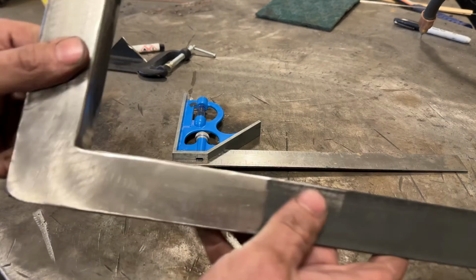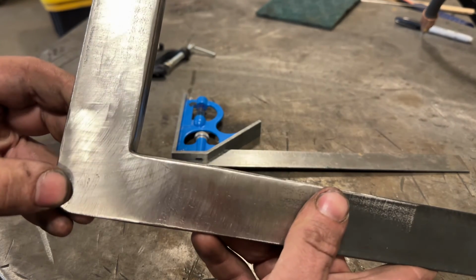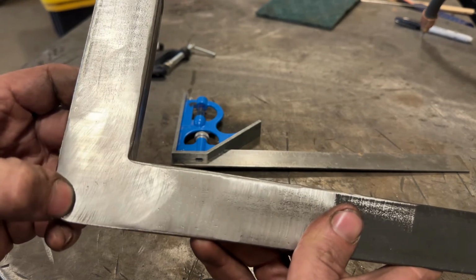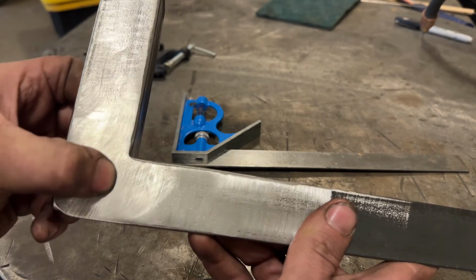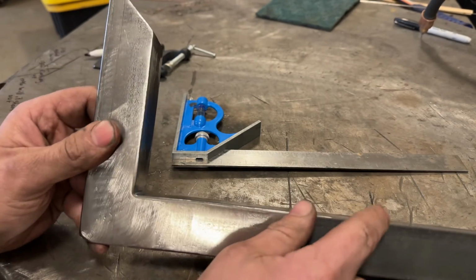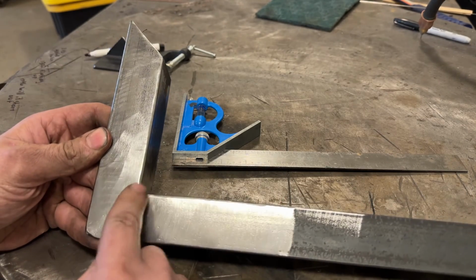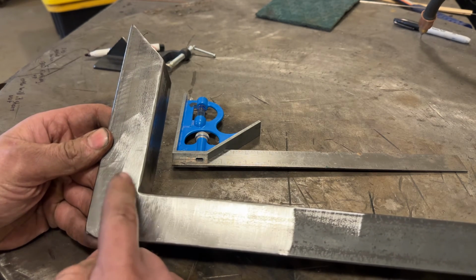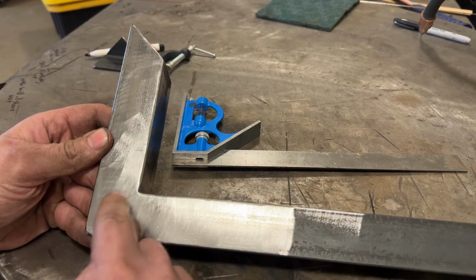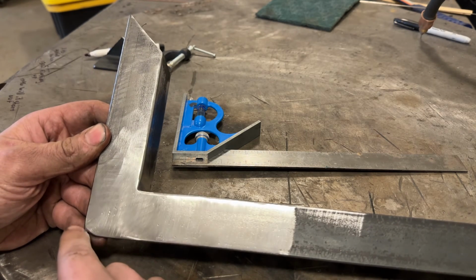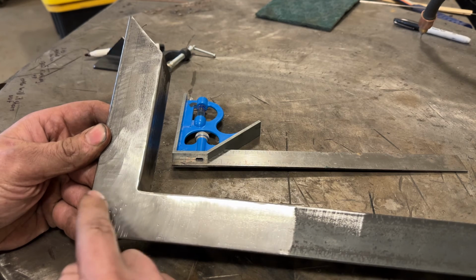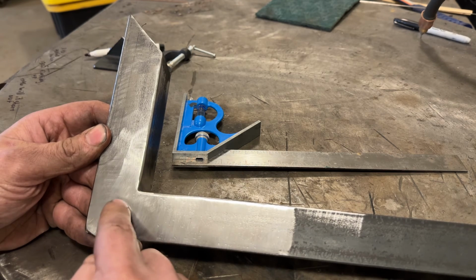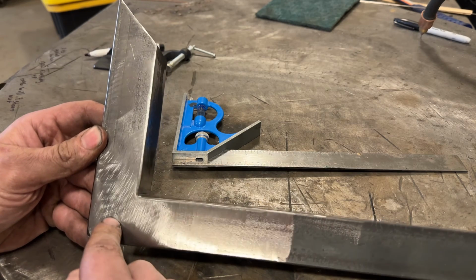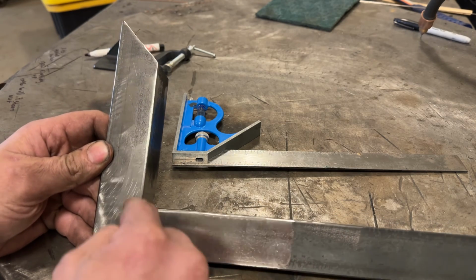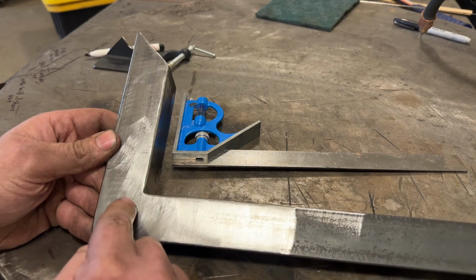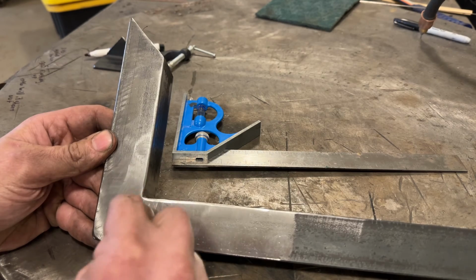I also want to mention, and I had said I don't commonly tack weld with flux core, that if you look here, you can see pin dot porosity after I ground the weld down. That's going to be very common with flux core, and I even brushed all the slag and flux off the weld before; I'd tack it, clean it, tack it, and I still have that. Part of it is I welded one side after the other side was welded, and it likely brought some contaminants through, but even so, it's very common with flux core. In order to prevent this, I would have had to run much higher values, and those higher values may have caused enough heat input to warp this.